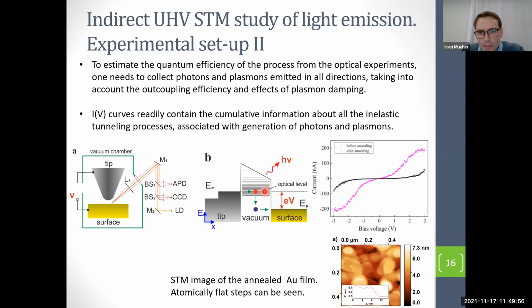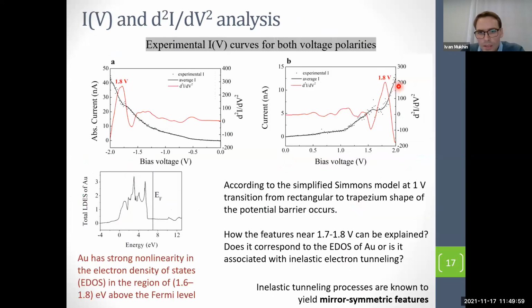Firstly, we see a change of slope of the IV curves around 1 volt. This change can be described by a simplified model: close to 1 volt, a transition from rectangular to trapezoidal shape of the potential barrier. So it's a very well known fact. Okay, but we have some features at 1.8 volts. These features are more pronounced when we study the second derivative of tunnel current on voltage.